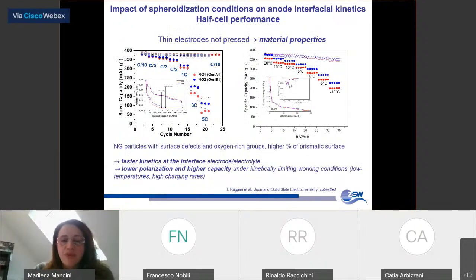What this means in terms of performance, in half cell measurements, when we use very thin electrodes and not applying any pressure, we are able to directly correlate the electrochemical response to material properties and get rid of all these parameters related to the geometry and parameters at the electrode level. And in this case, we see that natural graphite particles with surface defects and oxygen-rich group, and especially high share of prismatic surface, offer faster kinetic at the interface, electrode-electrolyte, and lower polarization, which then correspond to higher capacity under kinetically limited working conditions, in this case, low temperature and also high charging rates.